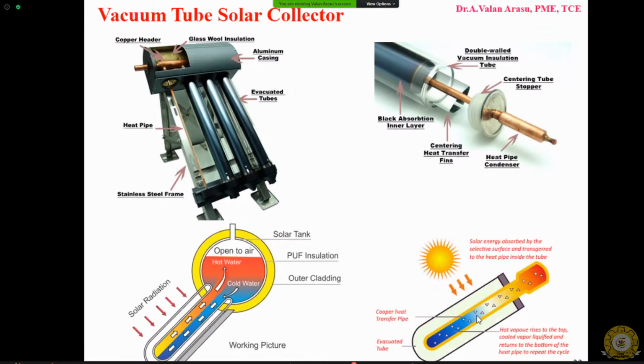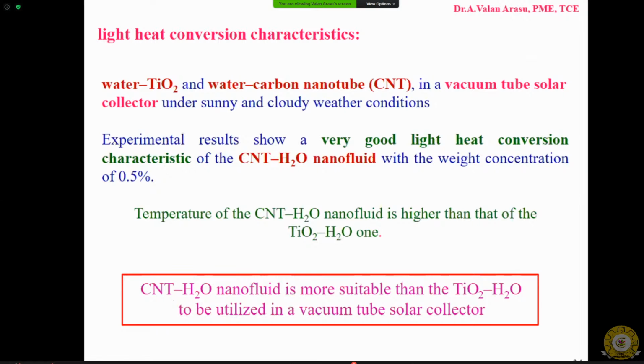but the important advantage of this collector is that the heat transfer surface is completely surrounded by a vacuum glass pipe. Okay. So there is no fluid in between. So convection heat transfer is reduced, and conduction heat transfer between this tube and the surrounding air is reduced. So heat loss is minimized as compared to the flat plate collector. So the efficiency of this collector is, though it is costlier, higher than the flat plate collector.